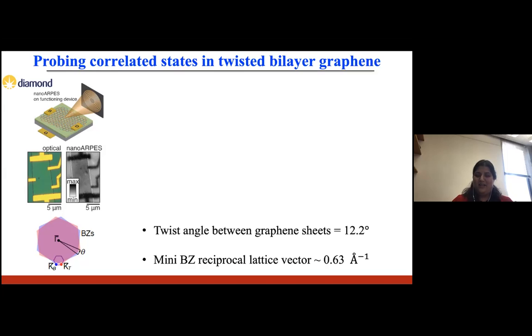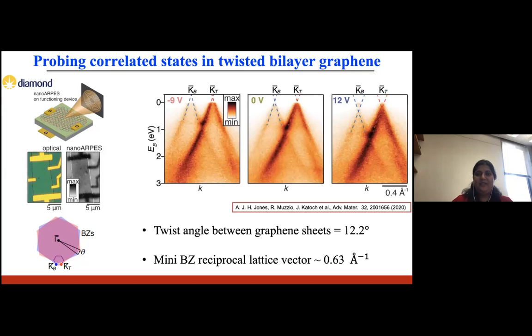But in our study, we have an 11 times larger mini Brillouin zone, and so we can do a more detailed analysis. And this part of the measurements was done at Diamond Synchrotron in the UK. Here I'm showing the ARPES spectra for 3 different gate voltages, along the line connecting the K points of the top and the bottom graphene. And you can see at 12-degree twist angle, we have a spectrum with 2 separated non-interacting graphene Dirac cones